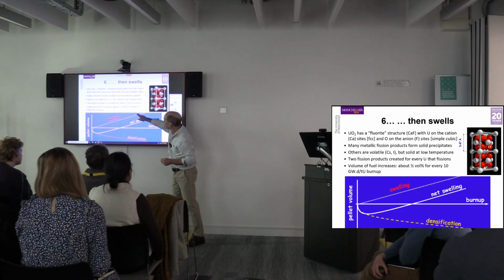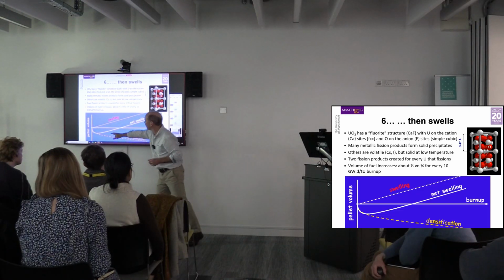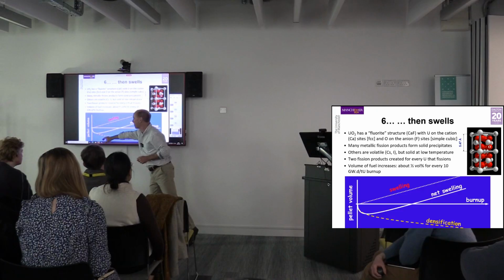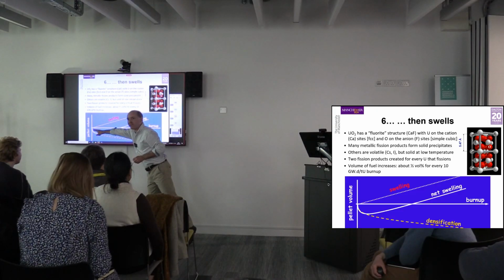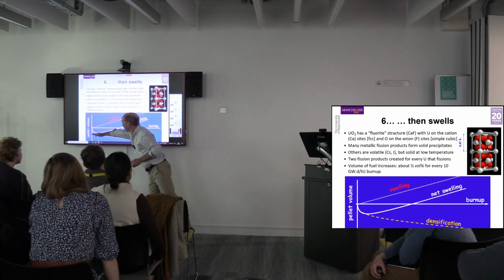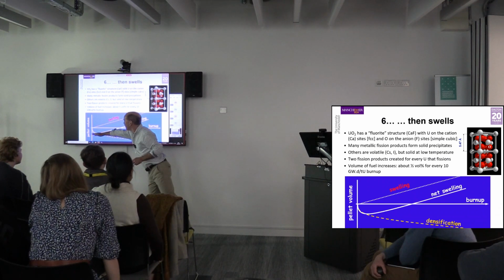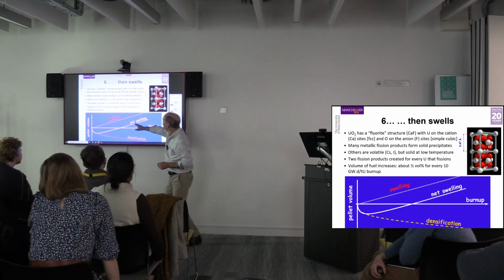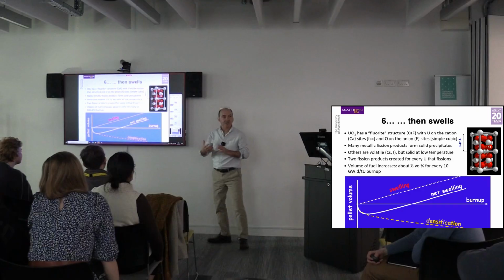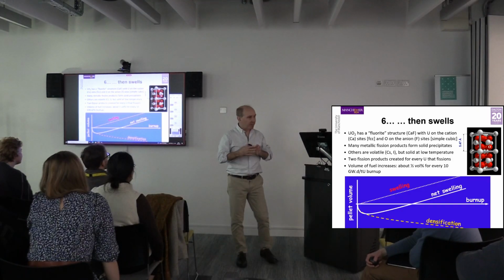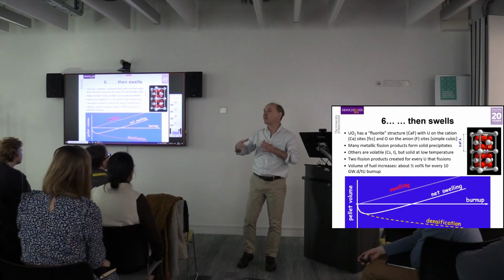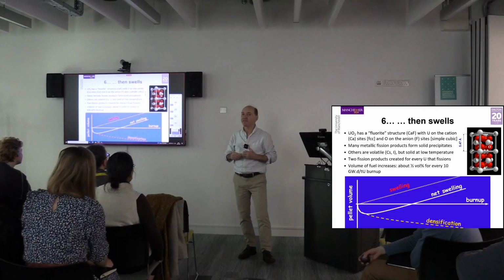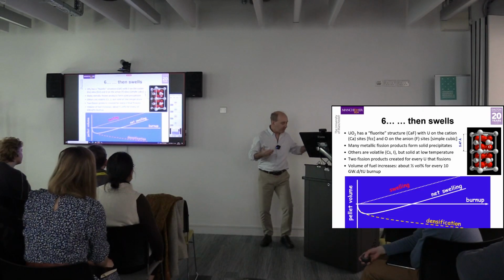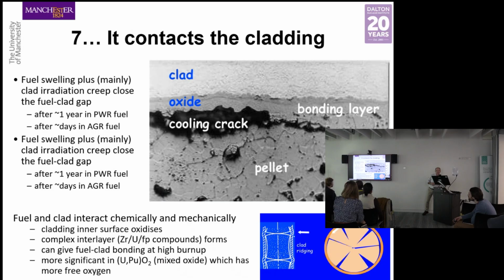And if you add those two effects together, you get something that looks like the Nike swoosh. So initially, the pellet shrinks, and then we hit a sort of a minimum pellet diameter, and from that point onwards, the swelling just continues. And that fuel pellet will continue to get bigger and bigger and bigger the more we leave it in the reactor. So we've got all these effects going on at the same time.